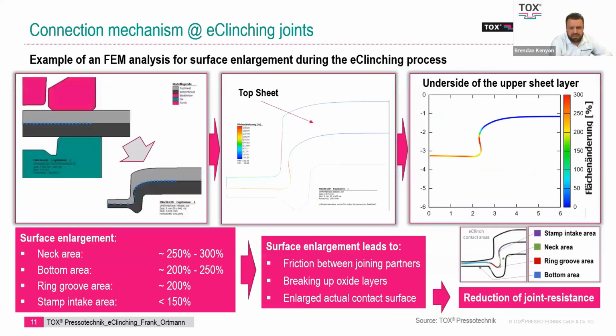So to further explain, you can see on an FEM analysis of the surface distance of the two faying pieces of material, as you deform and elongate that surface, that breaks up the oxide layers and it smooths out the roughness, and it'll increase the actual contact area. And in the neck area, we're seeing anywhere from 250 to 300% increase in that surface enlargement, along with that bottom area. But it's really key that it's within that neck area because you're able to withstand that residual mechanical stress, and to ensure contact between your layers of material.